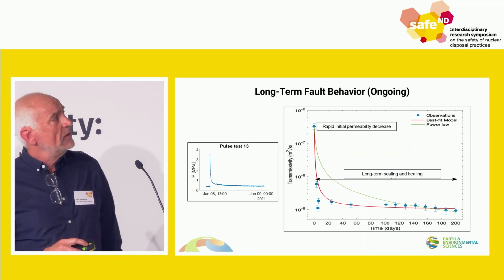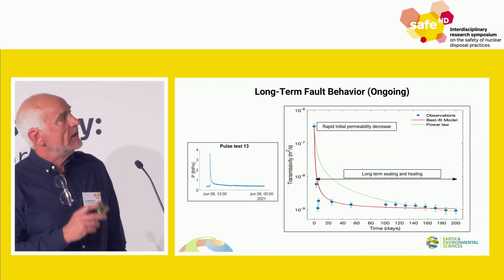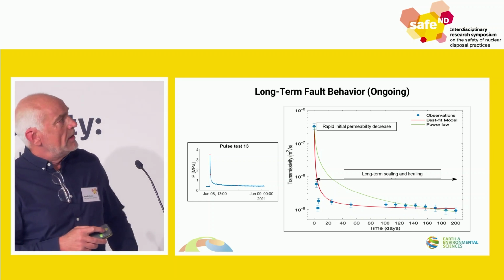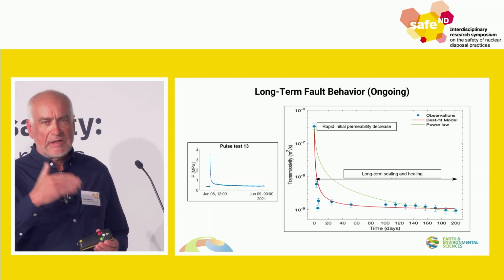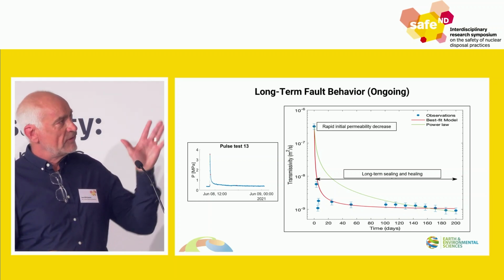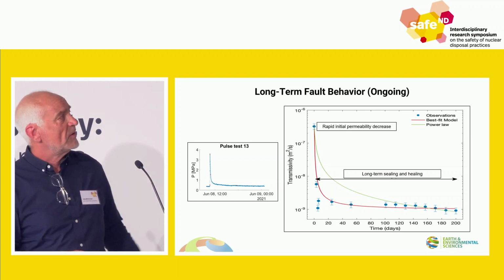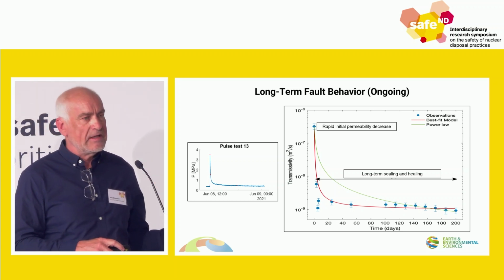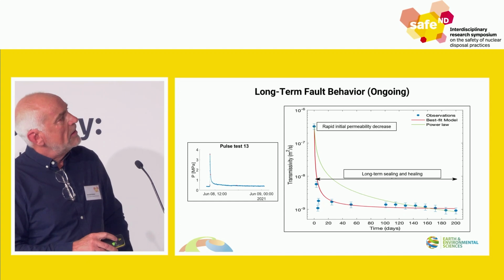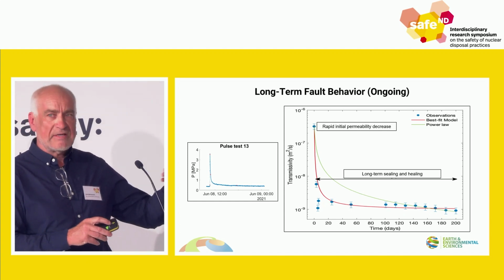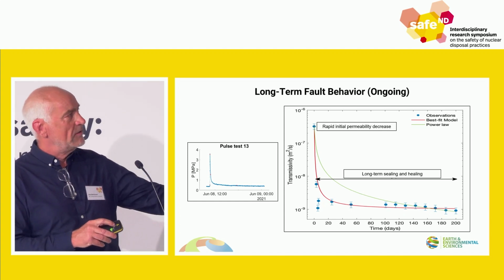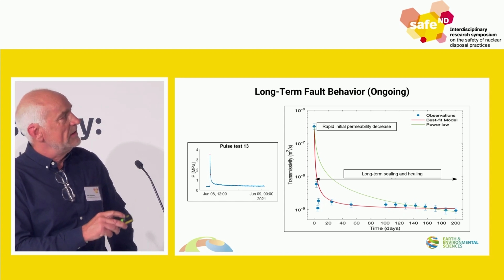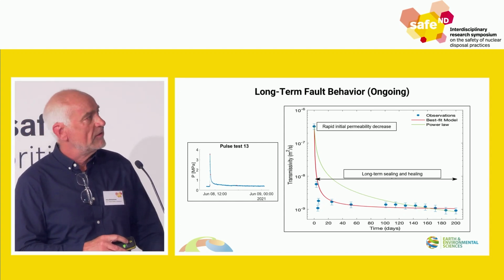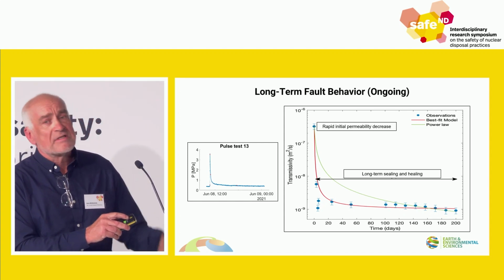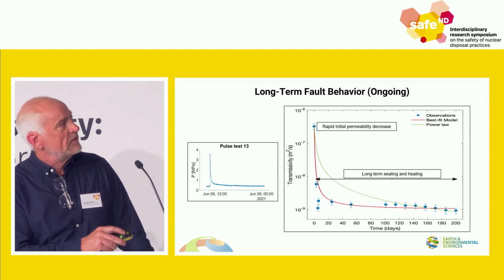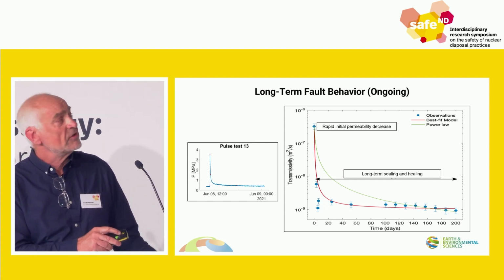Just to take a quick look at the long-term behavior, we did some pulse testing every few weeks or so after that first experimental series in 2020, over 2 years. We stopped basically injecting a lot in order to trigger; we just did these little injections, and that tells us something about the permeability. Once the pressure goes down, you get the rapid permeability decrease, which is good.